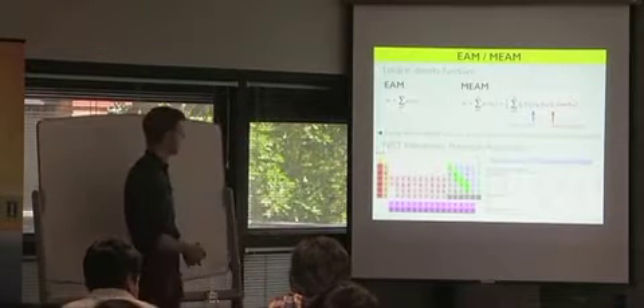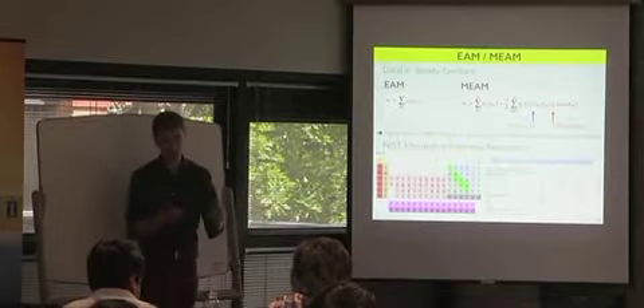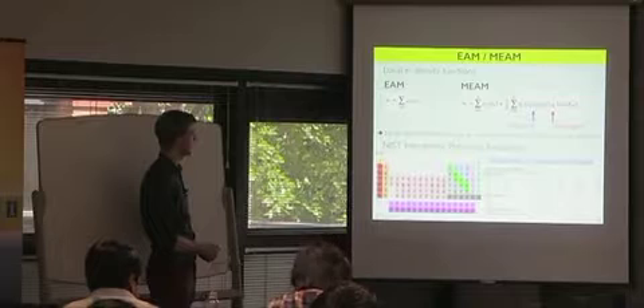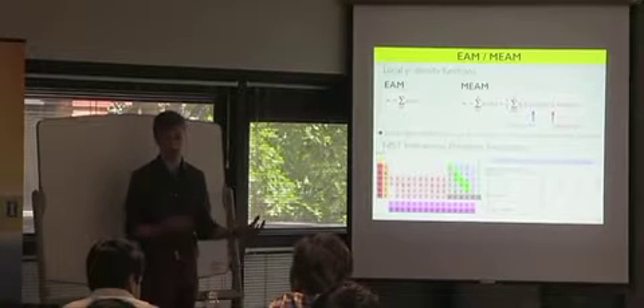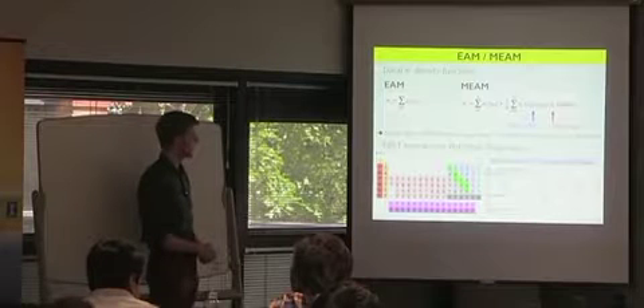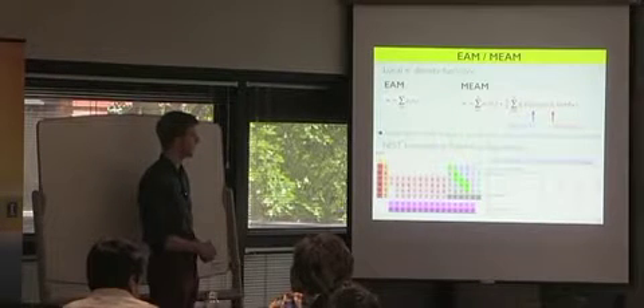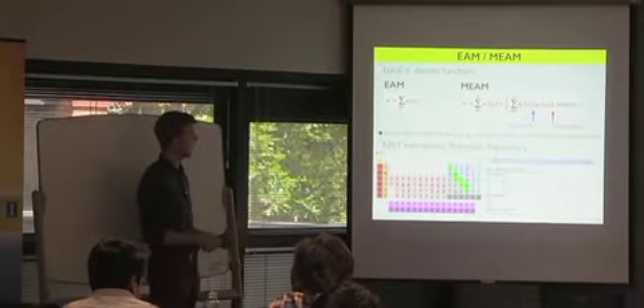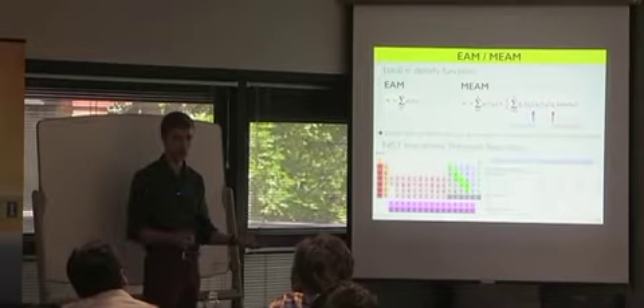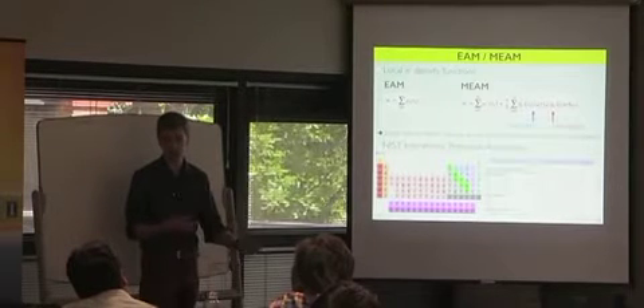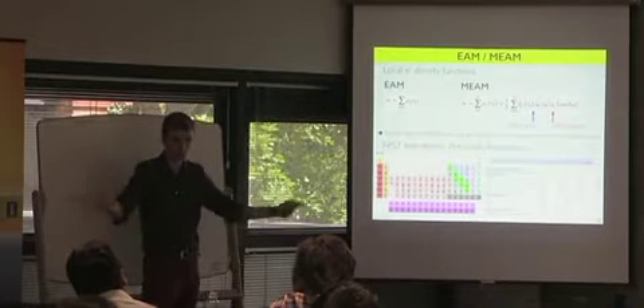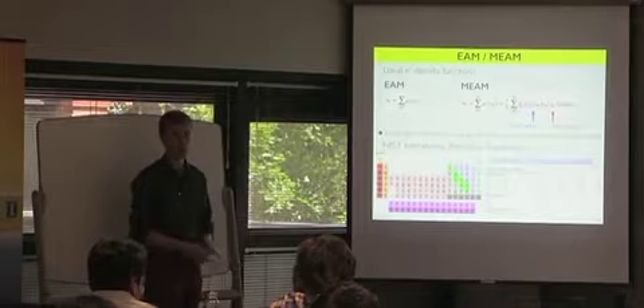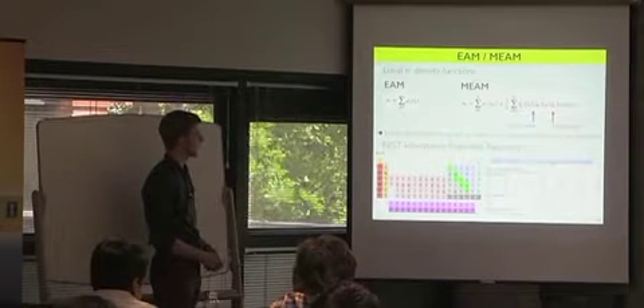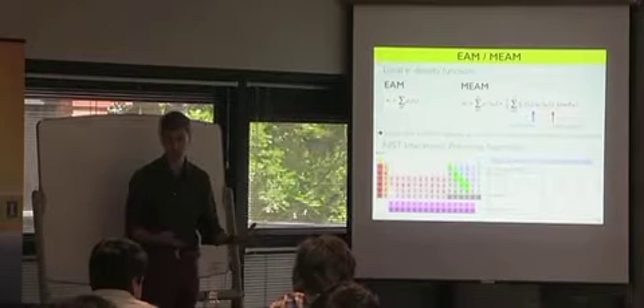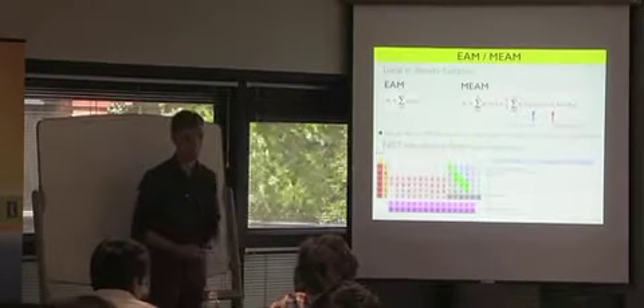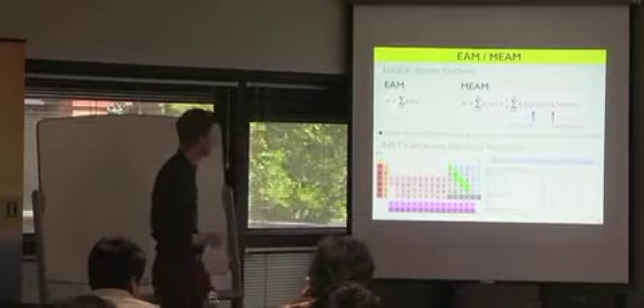Okay, so what's the difference between EAM and the modified EAM? In the EAM potential, we don't have any directionality, so that goes back to the question here, that the embedding function is just a function of the local density of electrons in your vicinity. In the MEAM potential, we actually have some directionality. So it's not just the local density, we actually worry about radial and angular contributions. The reason for this is it's very hard to simulate crystals with complex structures, so HCP, diamond, things like that, with just the EAM potential. We actually need to worry about the directionality of bonds in the crystal. And the MEAM can give you that. So you're going to need this for things like BCC, HCP, diamond. We're going to look at FCC aluminum today, in which case we can get away with an EAM. But you should be aware that for more complex architectures, you might need something like a MEAM.